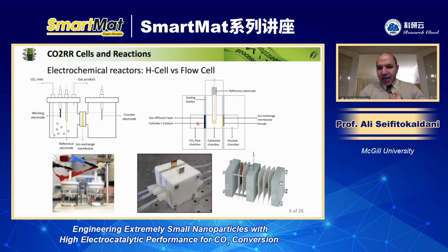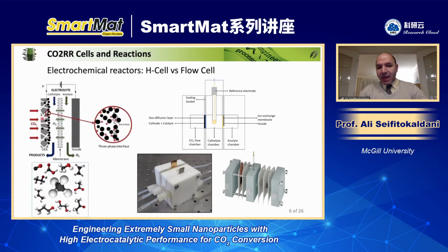So here you see that there is a channel for the CO2, which is separated from the electrolyte that we often call the catholyte. And now it can be any type of electrolyte that you want, from acidic electrolyte to neutral, which people usually used in H-cell systems, all the way to alkaline electrolytes, such as very saturated potassium hydroxide. But then this catalyst needs to be on a support which is porous. And the support needs to let the gas pass through and reach the surface of the catalyst to be converted. And here you see again a schematic of our system.